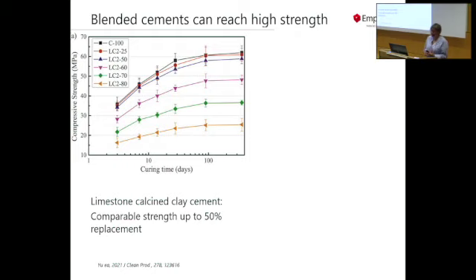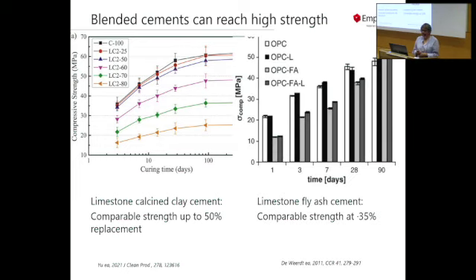I wanted to show some strength data. This is from a LC3 cement, where you can see up to maybe 50% of replacement. You get very nice compressive strength. You can get a similar picture also for fly ash cement, although there you have to get a bit lower replacement, maybe 35. And I'm sure you also can get similar pictures for the OPC cement or whatever you choose to mix.